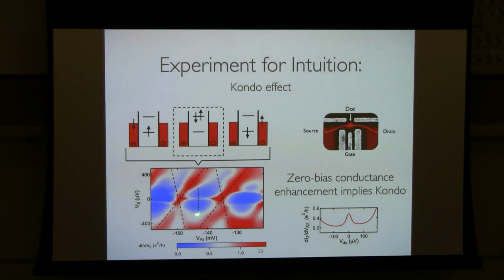And so normally, if you looked at that old artificial atom that I showed you, that should be a situation where no current flows through the system. But in fact, this color scale is showing the conductance, and there's a reasonably high conductance in this region where there should be none. And this is because of the Kondo effect.